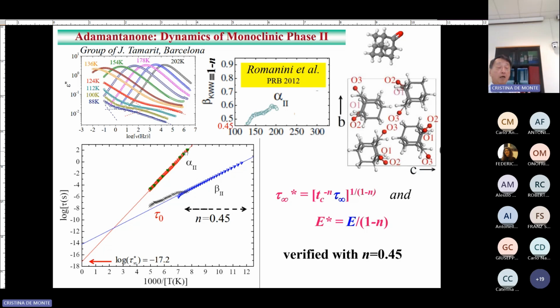Okay, then I can operate with this beautiful experimental data. All the known parameters, 1 minus n is known here. And then the TC is known. This is from neutron scattering before. For many of these materials, TC is about 1 picosecond. So we know this number. This is also from the coupling model, but experimentally determined from neutron scattering or by other means. I wouldn't explain further the reason for this TC to be a constant value, but that's a known quantity. So use the right-hand side of this equation.